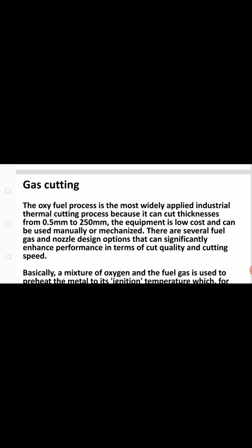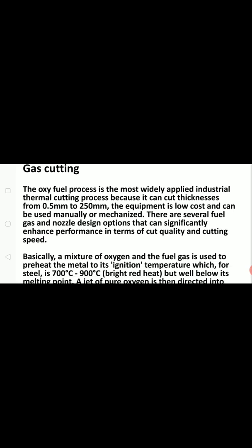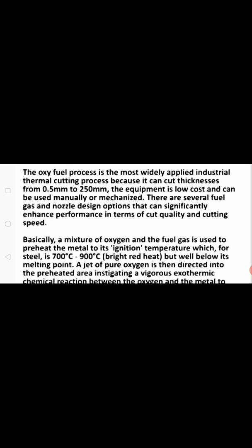Then coming to gas cutting: this is an oxy-fuel process, the most widely applied industrial thermal cutting process because it can cut thicknesses from 0.5 mm to 250 mm. The equipment is low cost and can be used manually or mechanized. There are several fuel gas and nozzle design options that can significantly enhance performance in terms of cut quality and cutting speed. Basically, a mixture of oxygen and fuel gas is used to preheat the metal to its ignition temperature, which for steel is about 700 to 900 degrees centigrade. A bright red heat is obtained, but well below its melting point.